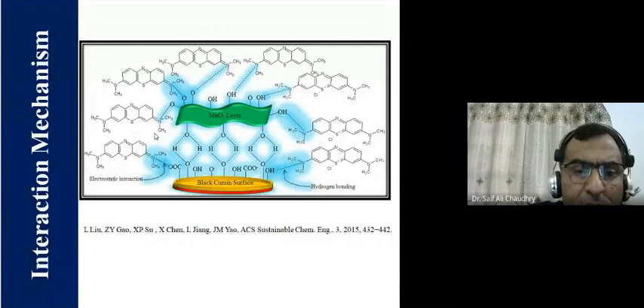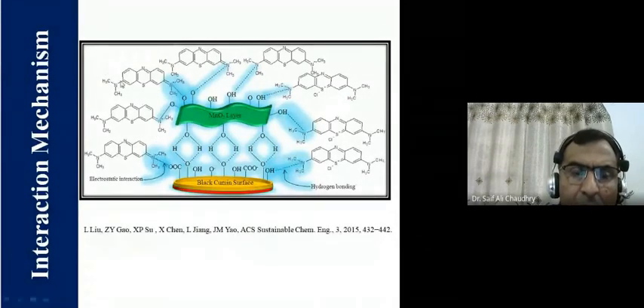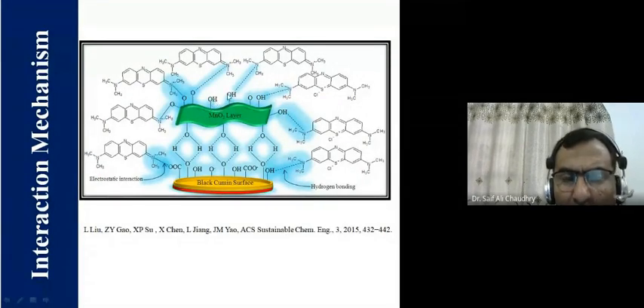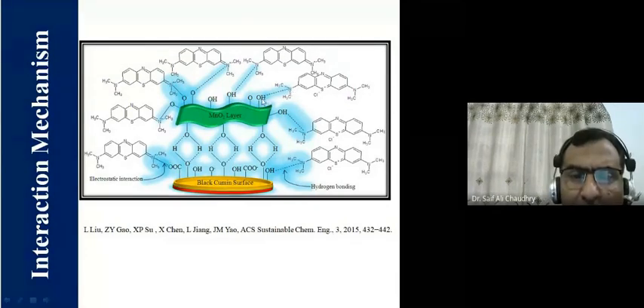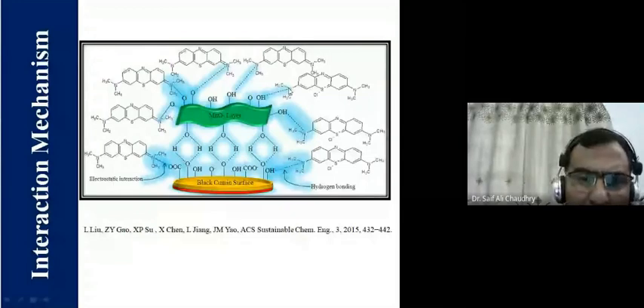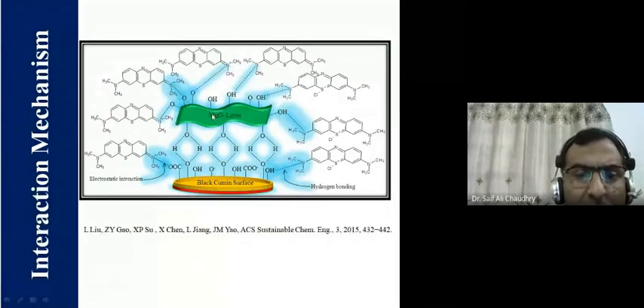The mechanism we have proposed, look at this. Manganese dioxide has OH hydroxyl groups present on the surface. They interact with nitrogen through hydrogen bonding. Methylene blue is a molecule where nitrogen is there, and there is a hydrogen bonding between oxygen and nitrogen through a hydrogen atom, right? Here again we have one electrostatic interaction. This nitrogen has a positive charge, it interacts with the manganese dioxide, and the materials have advantages.